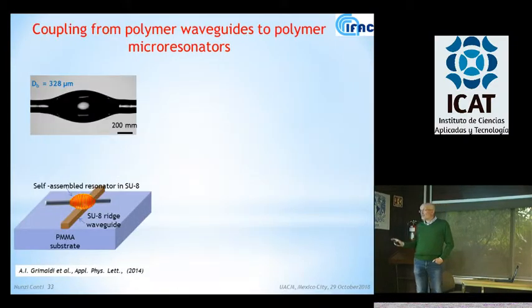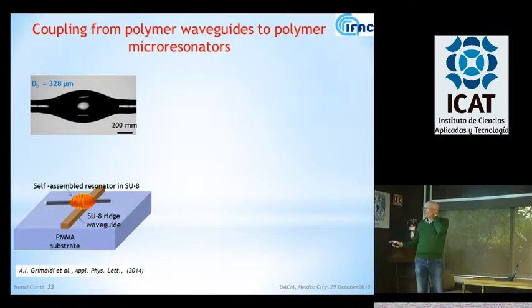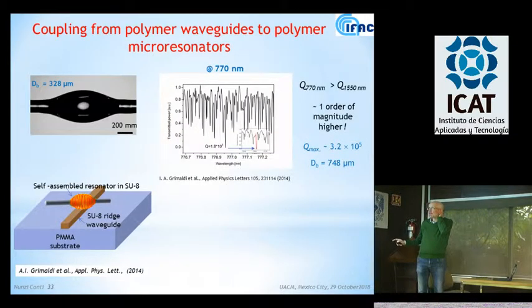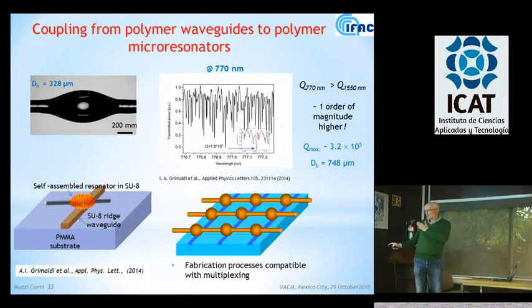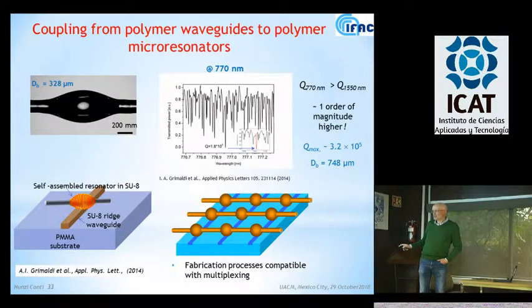This is the difference. The final results we obtained were with polymeric material. We wanted to couple light from, let's say, a polymer waveguide into a self-assembled microbubble resonator. This is basically made on a fiber on which this type of SU8 polymer is self-assembled. And well, here we could demonstrate coupling, and of course we could demonstrate that the absorption is much lower in SU8 at 770 nanometers, so we could get a Q factor one order of magnitude larger. And so this was also meant with the idea of being able to fabricate a type of multiplexing in which you can easily fabricate a polymer waveguide and also this self-assembled polymer resonator.